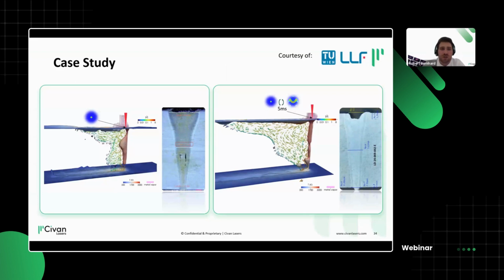This is usually also backed by simulation, where you see that when you use the single point in this case, or any other static beam shaping, you get a lot of cracking in the center. But when you start oscillating, you are able to stabilize the keyhole and even increase the size of the material. And I would argue in the end, most of this is a solidification problem in terms of thermal gradients. And this is definitely something we can adjust by changing the flow and also changing the energy input, how it goes into the weld seam.